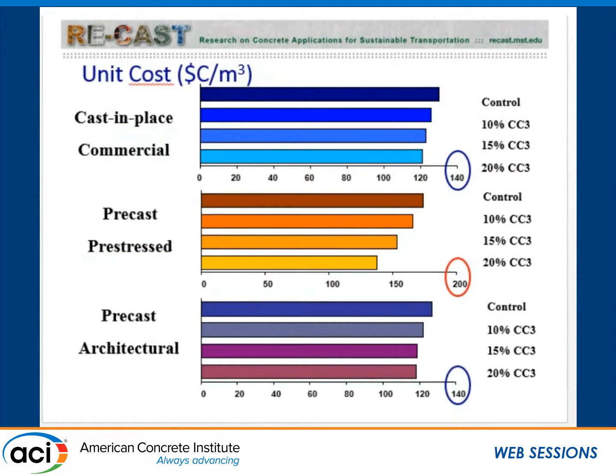The cost, it's always touchy to give these, but please consider this is Canadian dollars. It's about an exchange rate of 1.35, and these are numbers of 2007. So frankly, I don't know what the numbers are. We can take them as percentages. But the idea is that for the cast-in-place applications made with type 1 cement, whether you add limestone filler or not, you're not really getting much economy. Maybe a little bit of economy in this case because you are reducing the superplasticizer demand.